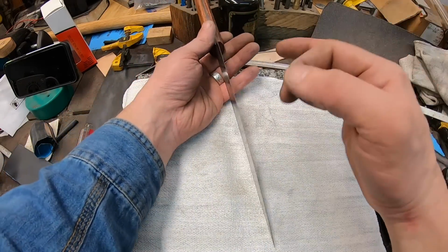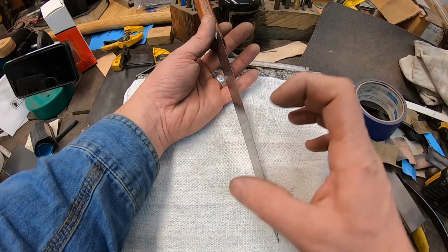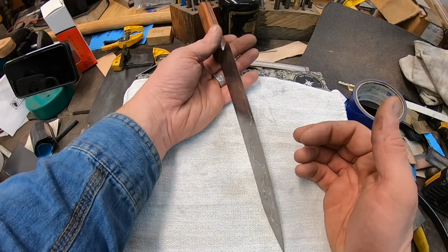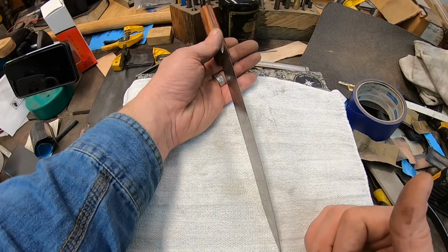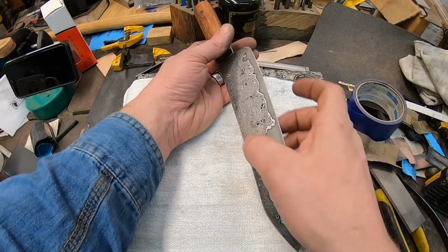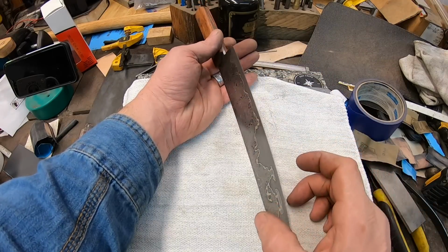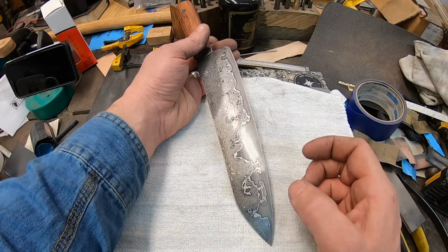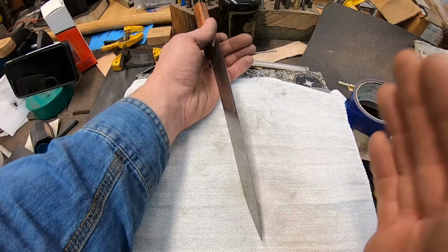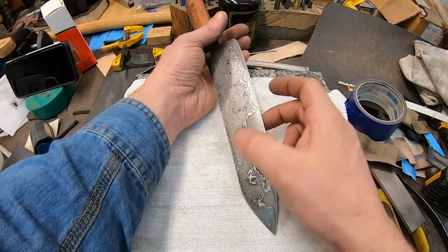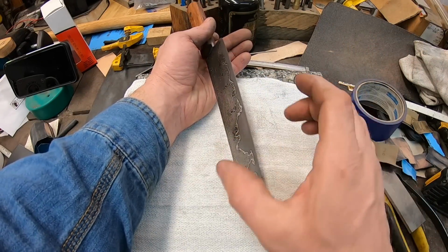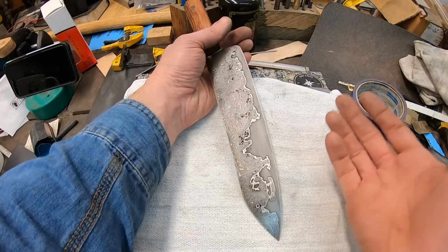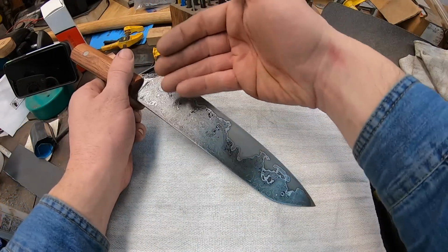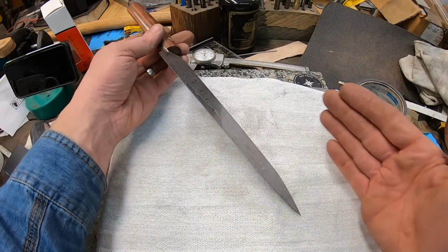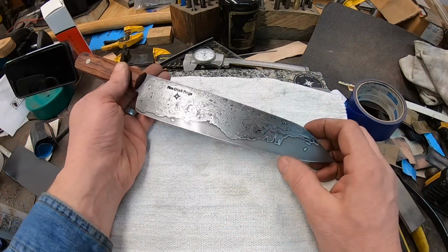And so if you have unequal hammer blows like that, and then you come back and straighten the whole thing without addressing those thickness and uniformity issues, then you're going to straighten the blade and it'll be straight, but your components in between are not necessarily in line. And so hopefully that makes sense. So then when you come to grind it and follow the straightness of the blade, you're revealing where some of that material had been pushed to one side or the other. So that could have been avoided.